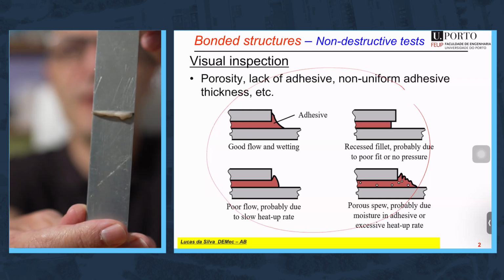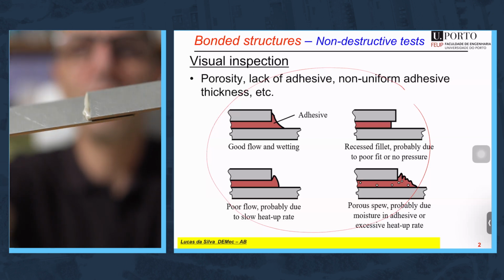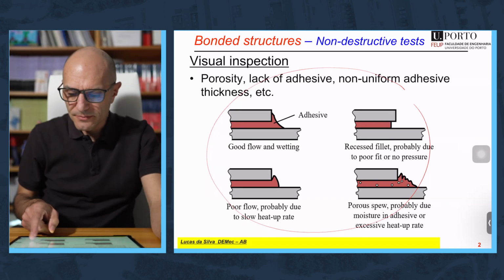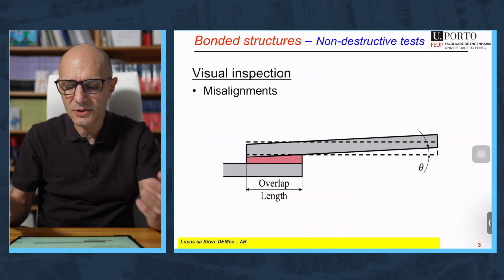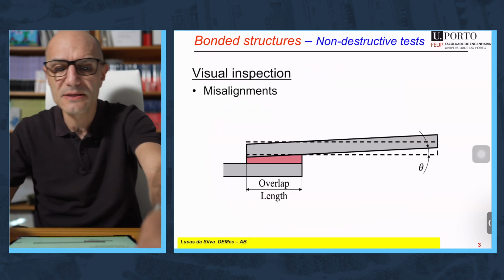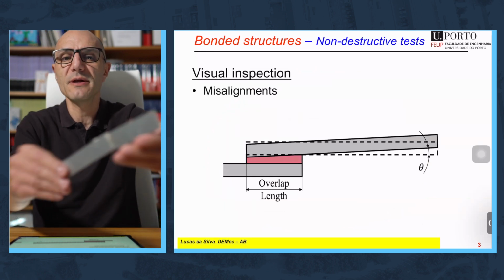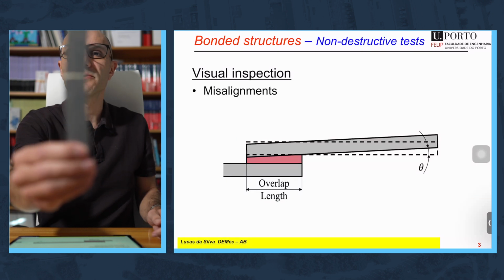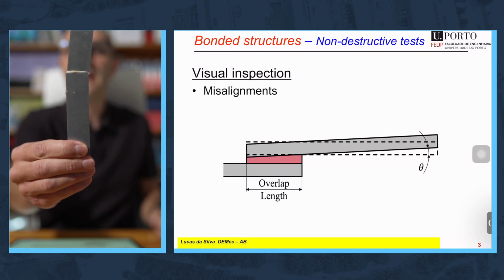This one, can you see the shape of the spew fillets? A very, very strange shape. Probably the viscosity was not right, the flow was not right, the wetting was not right. So this also does not look good. Then you have joints where there is a clear misalignment. It can be the adhesive thickness, but it can also be the alignment of the two substrates. I think this is more than obvious.